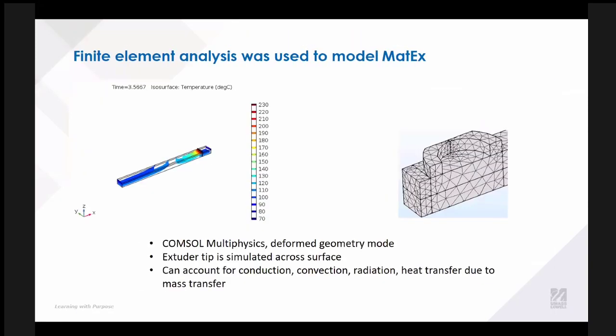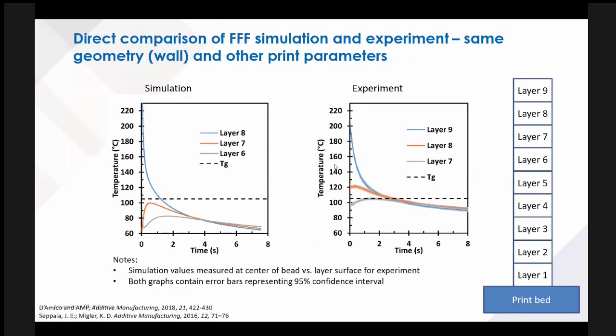I'm happy to talk about the details of the simulation with folks if you're interested. But this model allows us to account for conduction, convection, radiation, and heat transfer due to mass transfer. What we found is that for FFF, we don't need to account for radiation, which is convenient because radiation is very computationally intensive. What we are doing here is simulating this stainless steel nozzle moving across the surface and then extruding material within that nozzle space. When we compare our simulation to experimental results, we see that without any fitting, we end up having fairly good agreement in terms of the time scales and the temperatures.